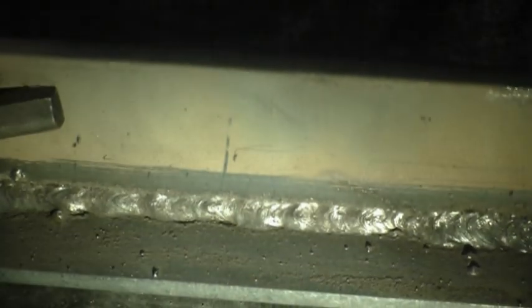So again, if I maintain a normal arc length and travel quick, I get a bead that is rough, and I have spatter, and I have undercut. I have unfilled areas. You can see this little hollow right where the brightness of the light is, with slag trapped in there. There's a shadow being cast. That's undercut. If I travel, again, a little too fast with the arc too long, well, if the arc lengthens, I'm really forced to slow down, because the arc, as it gets longer, it gets wider and it digs a larger hole, and the rod has to fill that hole in.